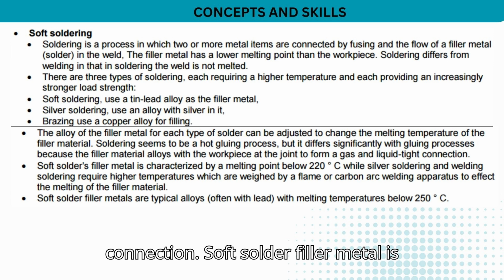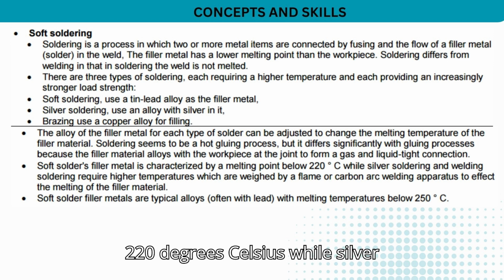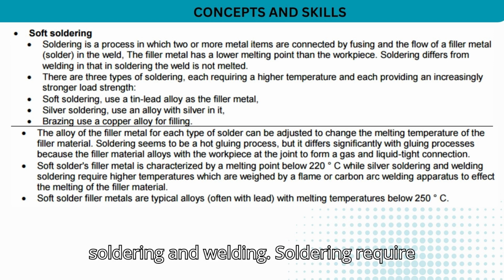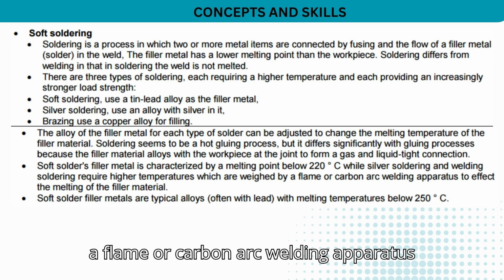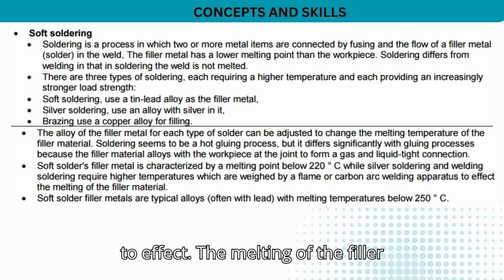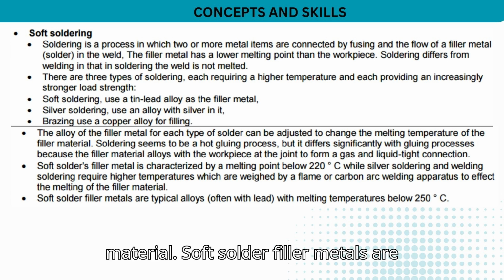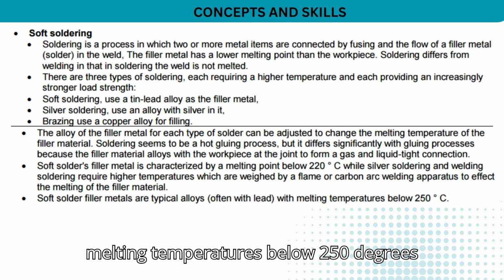Soft solder's filler metal is characterized by a melting point below 220 degrees Celsius, while silver soldering and welding require higher temperatures, which are achieved by a flame or carbon arc welding apparatus to effect the melting of the filler material. Soft solder filler metals are typical alloys, often with lead, with melting temperatures below 250 degrees Celsius.